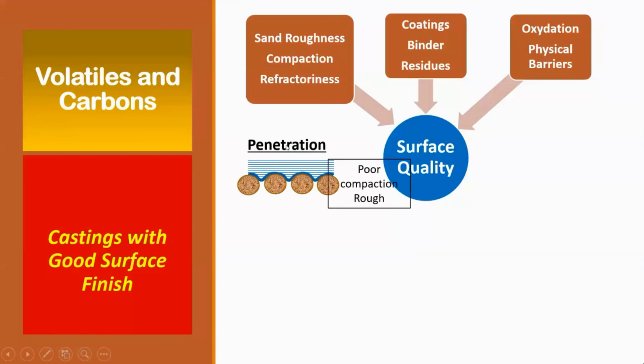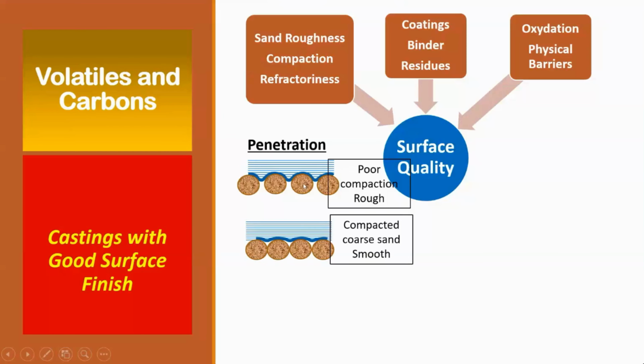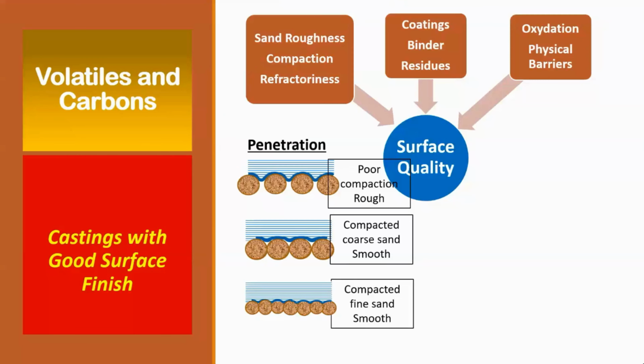We're talking about the sand roughness. You get a rough surface because of the penetration of the metal between the two sand grains. Sand grain roughness is one. Second is if it is not compacted well enough, then you will get a rough surface. If they are compacted well, it might be improved to a smoother surface. And if you are going to use a finer sand instead of a coarser sand, it will be smoother still. Now we talk about the barrier, which is an envelope of volatiles coming out of the volatiles addition with gas blanket theory. The gas blanket theory says if you have the metal like this here and then the mold here, then you get a gas blanket here, which is going to protect the mold from the hot metal.